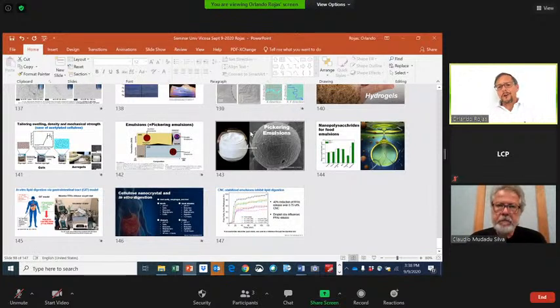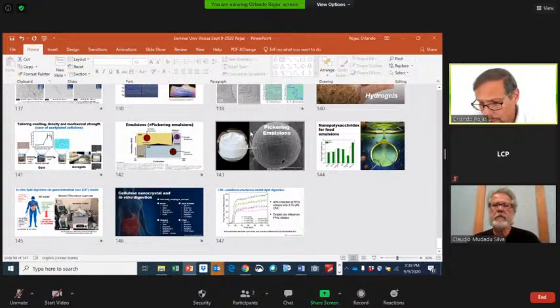And the yield, of course, is very important, but for nanofibrillar cellulose the yield is quite high. Not for nanocrystals. Nanocrystal cellulose yield is relatively low, even though there are reports, which you can read from my colleague Eero Kontturi, or also the work of J.Y. Zhu, where they report the production of CNC at actually pretty high yields. In the case of J.Y. Zhu, he reports the use of dicarboxylic acids to produce high-yield CNC combined with CNF. So while the typical sulfuric acid hydrolysis yield is pretty low, we're talking about 30% or in that ballpark, other methods can be quite high.